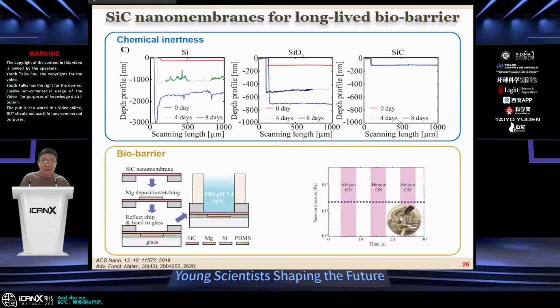And also, we want to use silicon carbide as a barrier to protect underlying electronics, like transistors for a bioamplifier. So we want to see how water and ions diffuse through the silicon carbide and attack the underlying electronics. The way that we test is to use a magnesium membrane, because magnesium is highly reactive with water. If you put magnesium in hot water, you see the reaction and the change of the surface by your naked eye. So we deposit magnesium on the outside of silicon carbide, put a reservoir on top, and then observe how water diffuses through the silicon carbide membrane. And before we did this test, we also confirmed with a helium leak test that the membrane was pinhole free.